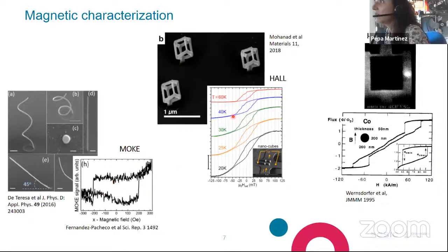Secondly, we have these Hall measurements, where you see some hysteresis curves obtained at different temperatures. These measurements are really beautiful because they were obtained measuring just these four three-dimensional iron cubes that you see here. There is a fourth cube below this graph. As you can see, Hall does offer the possibility, of course, of working at variable temperature and also under the application of very large magnetic fields.